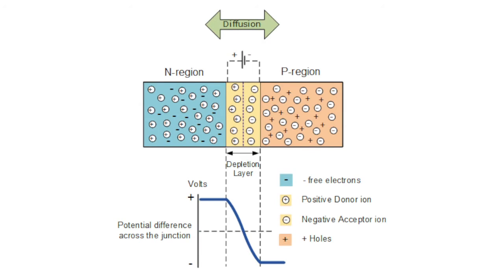What happens if you put a piece of N-type silicon next to a piece of P-type silicon? The electrons and holes will diffuse into one another for a small distance in what is called the depletion region. In manufacturing, they don't make two separate pieces and stick them together — they use one piece of silicon and dope the two parts differently, either by having a gas of dopant atoms diffuse into the silicon, or by ion implantation where high-energy ions of the dopants are shot into the silicon. Both processes require very low pressure conditions, basically a vacuum. Dopants can be directed using photolithography techniques which effectively shield some parts of the silicon chip. In this depletion layer, a voltage — a potential difference — develops as the electrons and holes diffuse.